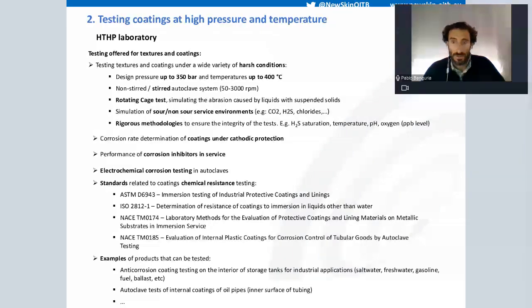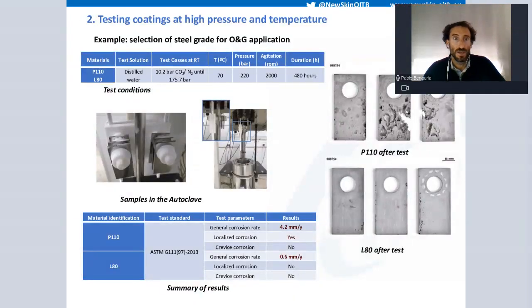Okay, next one is an example, the same as before. We had to select between two materials, P110 and L80, in a distilled water media under a temperature of 70 degrees and a high pressure of 220 bars, with agitation during almost 500 hours. We performed the testing, and we observed the general corrosion rate and the localized corrosion, which was quite higher in the first of the materials. So we concluded that the second material withstood much better the conditions that the customer needed.